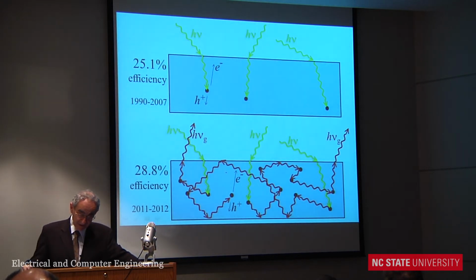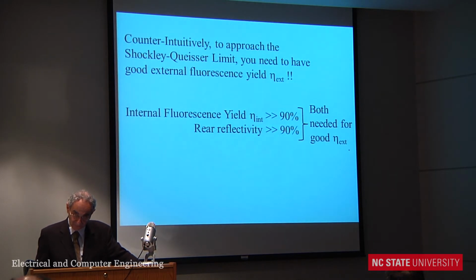And it comes from this mechanism. In order to get the high voltage, you need to have an internal luminescent photon gas. It's an absolute requirement to getting high voltage. And that photon gas has to be way more dense than the incident sunlight. The density increase could be as much as 4n squared. And so this becomes a requirement. And also you have to be able to get light out. That also becomes a requirement. That's decreed by Shockley. But it's hard because 90% is not enough.